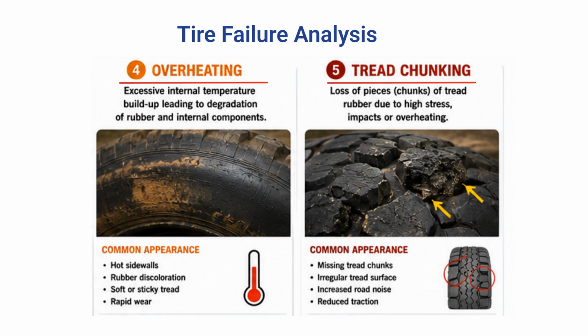Tread chunking is the loss of pieces of tread rubber caused by severe stress, impacts, or excessive heat. It appears as missing tread blocks, an irregular tread surface, increased road noise, and reduced traction. Common root causes include sharp or rocky terrain, high torque during rapid acceleration, an unsuitable tread compound, and overheating. Both failure modes reduce tyre reliability and may quickly affect vehicle mobility if they are not detected early. Regular inspection, correct inflation pressure, suitable loading, and controlled operating speed are therefore essential for prevention.